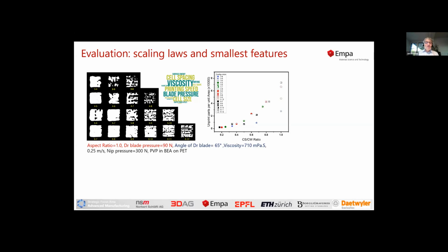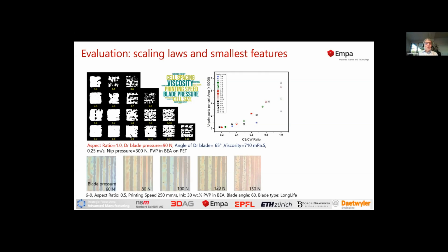So what we have by now is something like 20,000 images which we have to analyze. I cannot show the results yet, but in future you can contact us or look at our publications, and we hope that we can greatly contribute to an understanding of how cell geometry influences and affects the fidelity of the gravure printed pattern. We are also after the smallest line features we can print. We have not found the smallest features yet, but currently 8 micron is a very reliable conductive line from a silver nanoparticle ink which we can print.